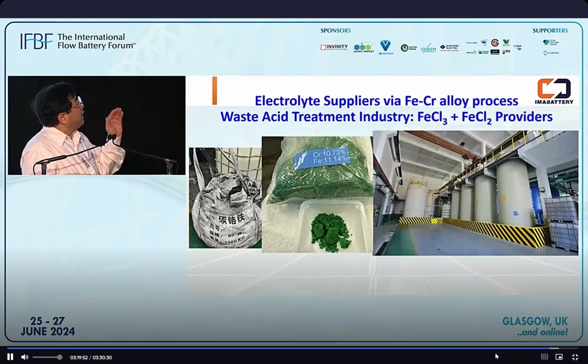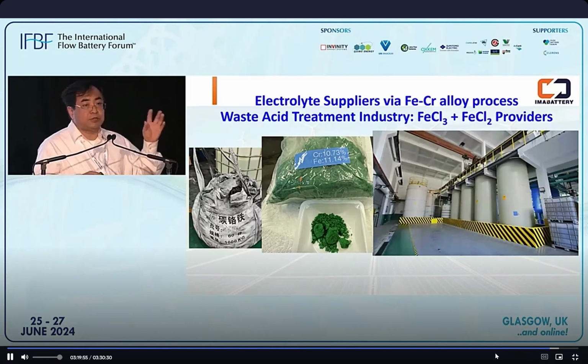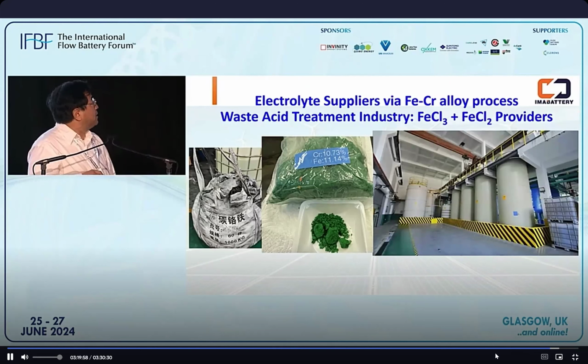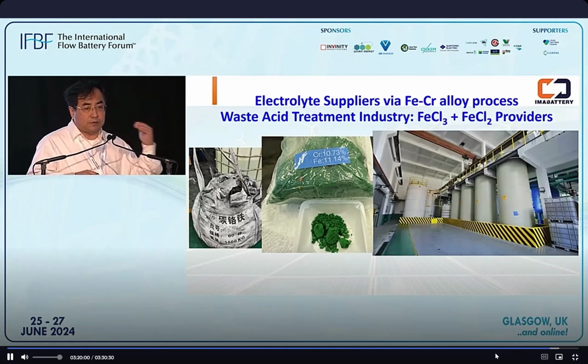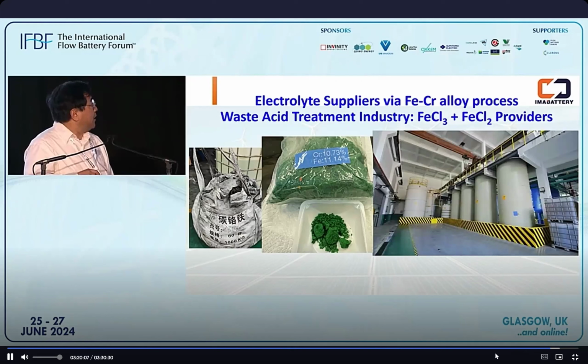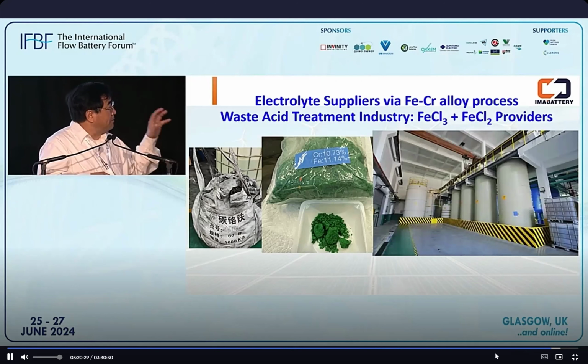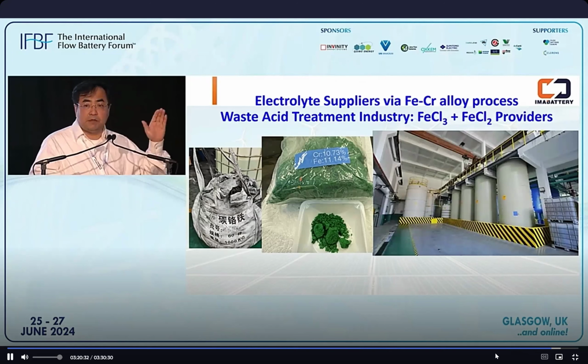We identified a huge industry, the waste acid treatment industry. Once you wash stainless steel to treat the surface, it generates a lot of waste acid solution. This solution is collected by iron chloride producers, and they make either iron chloride solution or high purity iron chloride salt. They already have all the equipment and all the process, even for the impurity removal.